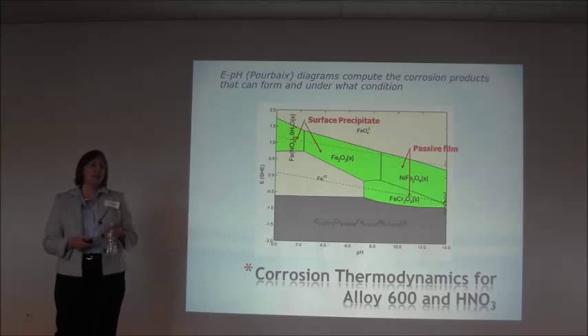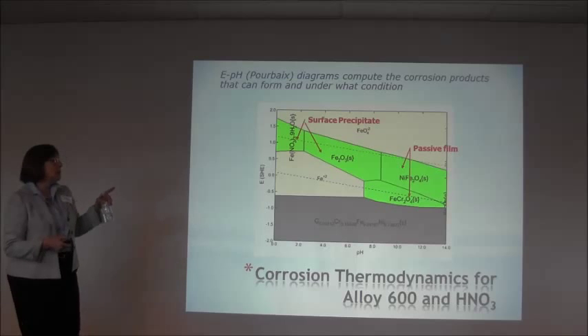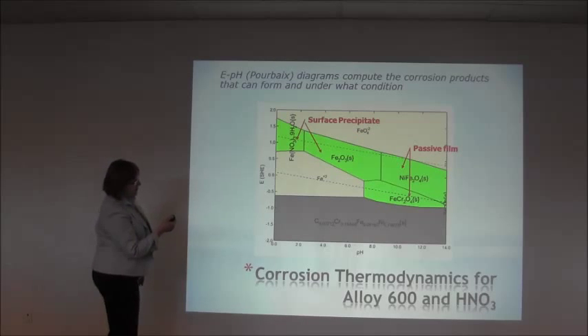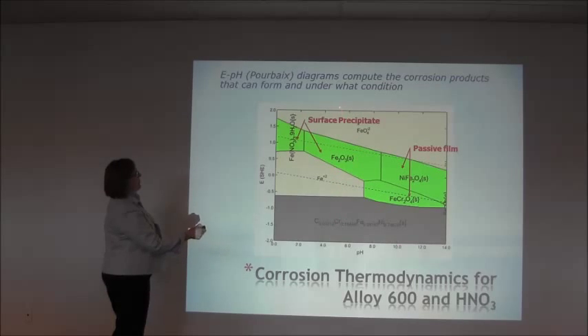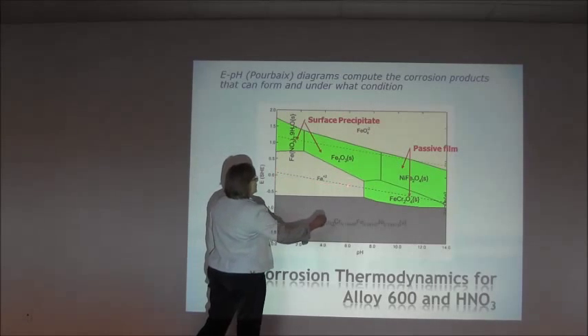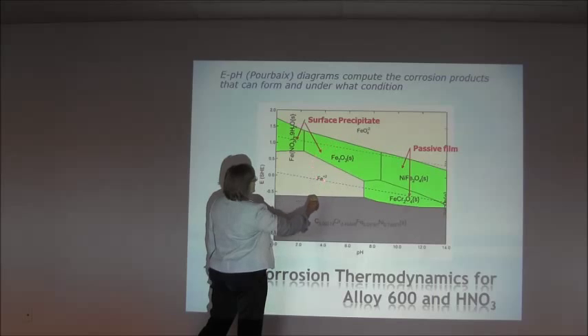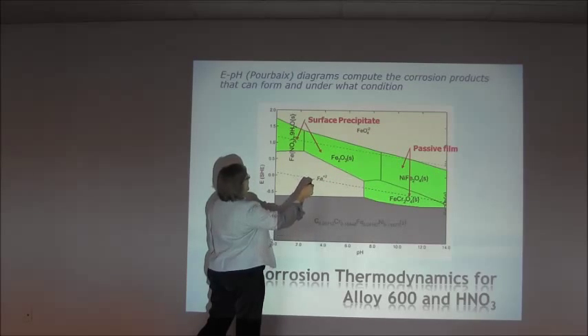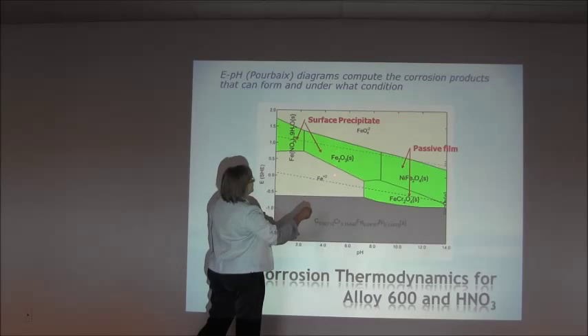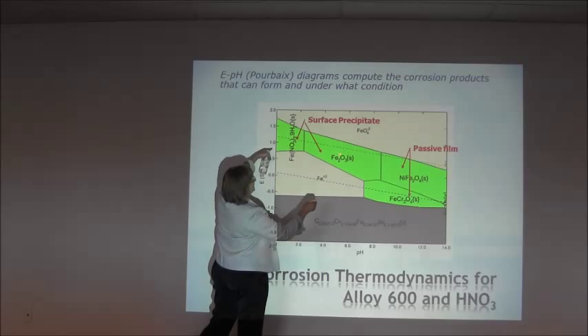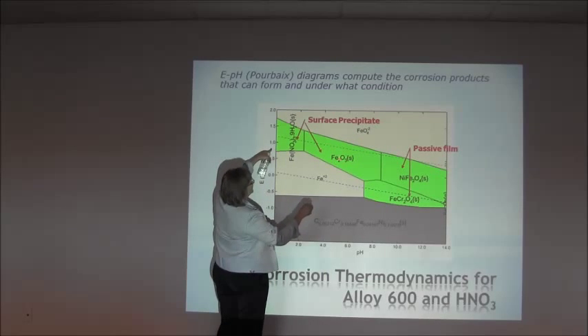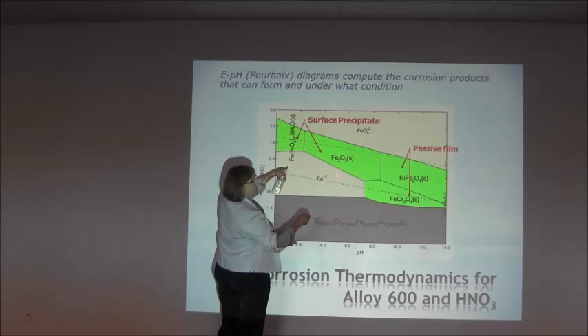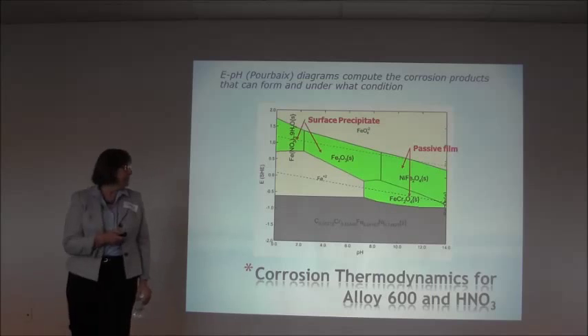So just by understanding the species and whether they're passive or inert, we can make predictions. What's missing from this? Then we usually have a line that says the natural pH of your solution is, let's say, 5.5. These two dotted lines are where life occurs. If you're below here or above there, you're not on Earth, you're not working with a solution in our atmosphere. So if we're looking right in here, and we get the electrical potential up into this area, then we're in the passivating region. But if we get less electrical potential in our system, we might have a corrosive situation. That's how you read those diagrams.